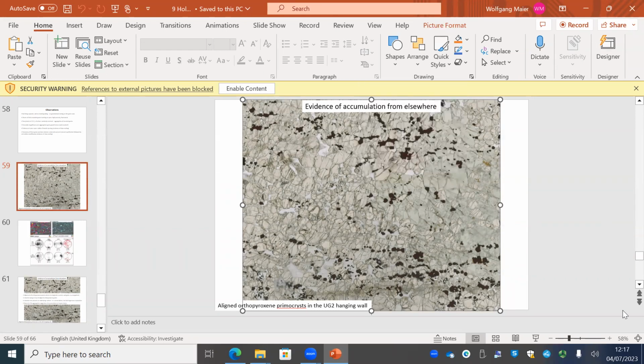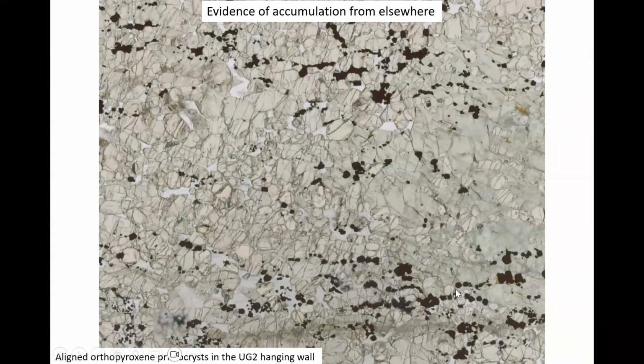We've got some tomography on basically that rock type, not from that cycle, but it's essentially the same rock type. The sample we looked at probably has a little bit more chromite in it than that, but not much. What we found is that those clusters are up to about 2 or 3 centimeters in size, so up to about 10 times the size of the orthopyroxene crystals. Which section do they go in? They're more or less parallel to the foliation, like you've shown there.